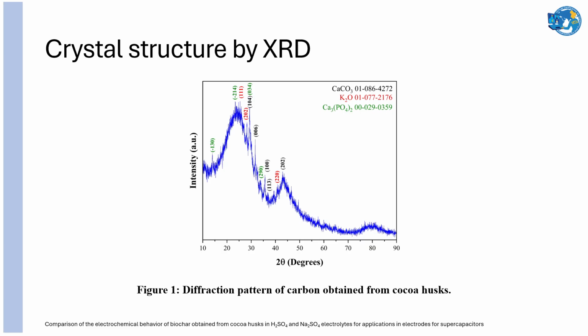XRD shows some common patterns related with pyrolytic carbon, but also some additional phases like calcium carbonate, potassium oxide, and some calcium phosphate, which is commonly found in some of these agricultural waste treated at very high temperatures.